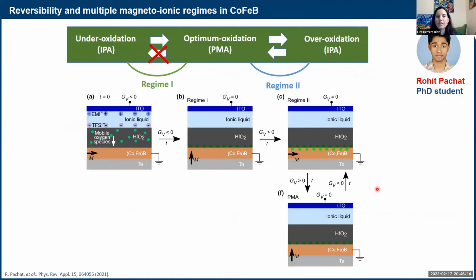So our interpretation of this is that when we start with an under-oxidized state, we have a surface that has barely any oxygen. So then all the oxygen binding sites are more or less available. If we assume that all oxygen binding sites are not equivalent, there are probably some binding sites that are more energy effective, more energy favorable than others. Those will probably be occupied first. So with this premise, we think that regime 1 is probably a regime in which these preferential oxygen binding sites get filled first. And then this leads to PMA.